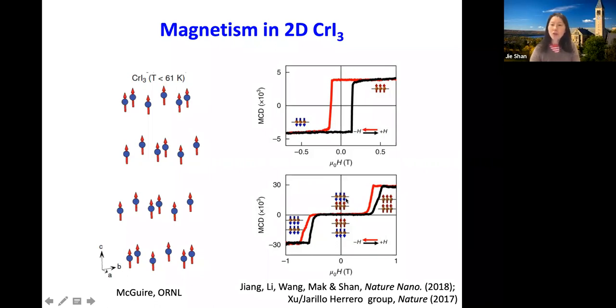Okay. So why the magnetism, in the bulk, is a ferromagnetic coupling between the layers, and then in very thin layers, it's antiferromagnetic coupling is an interesting topic by itself. So the key ingredient is exchange interaction is very sensitive to the stacking order between the layers. So that's kind of a difference. And I'm not going to talk about this. So let's just agree on the experimental fact that in four-layer chromium iodide, we have antiferromagnetic interaction as ground state.